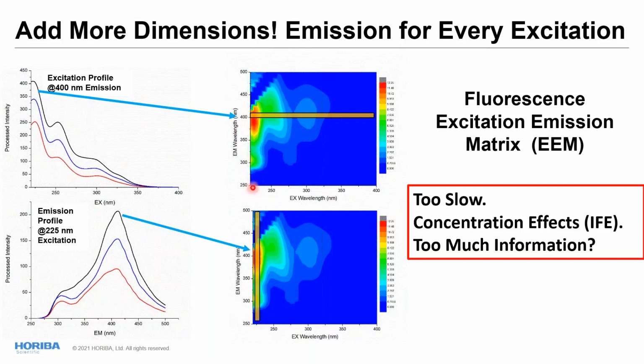Standard EEMs are collected by tuning the excitation, and then with a single point detector detecting the points along this axis, and then stepping onto the next excitation wavelength, building up the emission profile. So this can be very slow for collecting a full EEM profile of a sample. So that's the first potential issue we see with this. The other is that fluorescence is known for self-absorbance interfering with the sample profiles, and this is called the inner filter effect. And it can shift the EEM features in a concentration-dependent way. So if you have a fingerprint that is concentration dependent, as coming from Raman and FTIR, I would argue that may not really be a fingerprint.